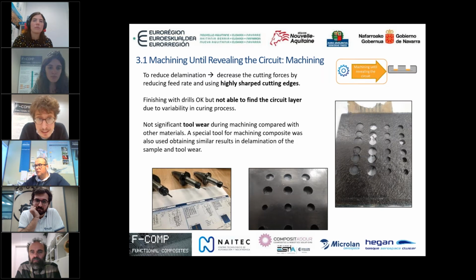Another point that was included in this task is trying to reveal the contact points for doing the additive, the next step, that is adding the copper to the contact. So in this case, MICROLAN used a drill process for trying to reveal the position of the contact, and it was seen that not having an external reference, or not having considered it since the beginning, makes it very difficult to reveal the contact, as it is not possible to take a proper reference. Regarding the wear of the tool for the drilling, as per MICROLAN's experience, it is not a big issue. Guillem, later on, if you want to further explain, we will have a moment. Okay, I continue with this, and later on we go in further detail.